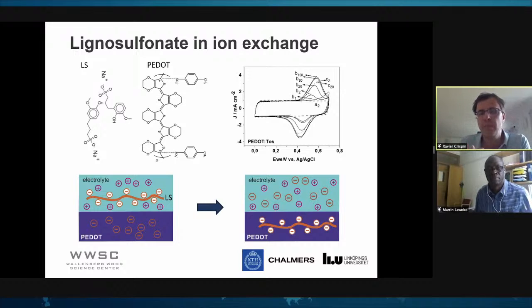So it means that these polymers are easily swelling by the solvent, and that is enough for even the lignosulfonate to come and go inside the material and completely change the material over something like 100 nanometer thickness. So we could form this first nanoparticle of PEDOT tosylate, dip it in lignosulfonate and completely ion exchange, and we get a material for battery in a very simple way. If you do that with a lignin with carboxylic acid, it would of course be very interesting. Just tuning the pH, and you will be able to do that. I guess it would be interesting.